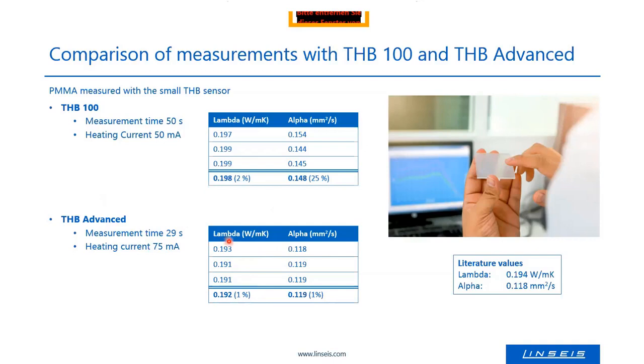The accuracy is also very good. In this case, three measurements have been performed and averaged, so it's 0.192, within 1% of the literature value. And now you can see this is a very good thing: the alpha, the thermal diffusivity, we can measure now, due to the much better time resolution of the experiment, also within 1% for plastics.